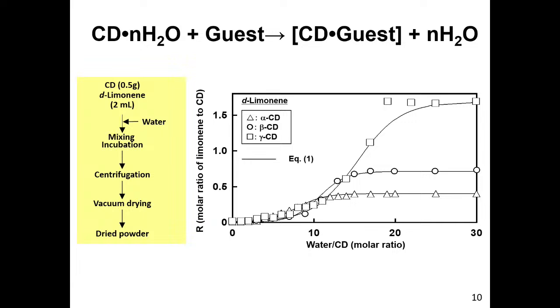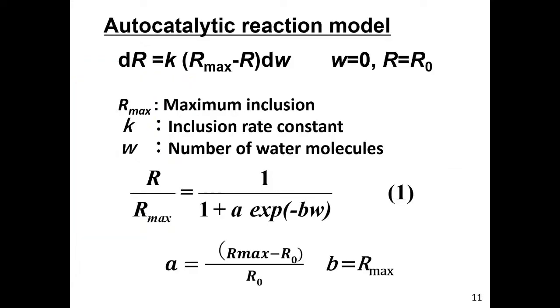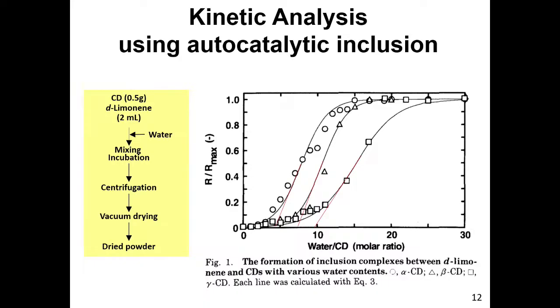They need a high water content. At no water case, we cannot get the inclusion complex. So this is some autocatalytic reaction model, and we can get this kind of curve.